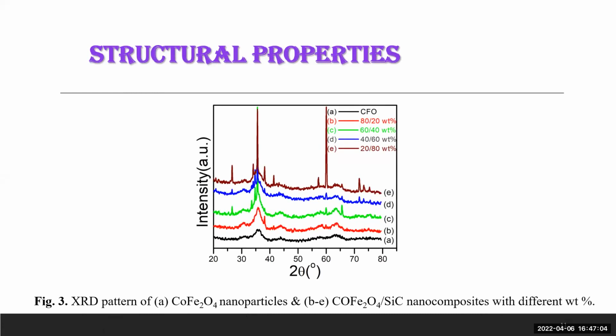The XRD pattern shows that all the samples have a single phase of cubic spinel structure, which was confirmed by the JCPDS file. The 311 plane of the cobalt ferrite nanoparticle and the 111 plane of the silicon carbide confirm the proper attachment of silicon carbide with cobalt ferrite nanoparticles and the formation of the nanocomposite in a proper phase.